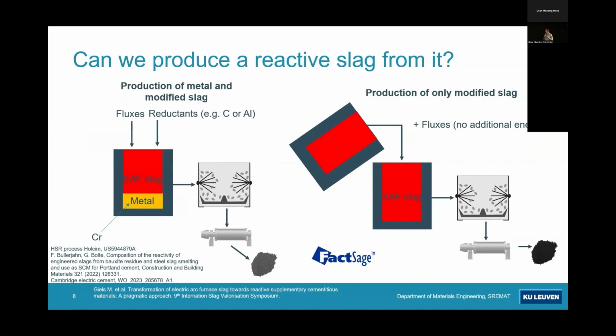There you actually take the electric arc furnace slag, but you add reductants such as carbon. You can also use aluminium, like aluminium drosses can be something interesting to produce a metal. And there you actually extract the metal. You can capture chrome and vanadium. And then you have a slag which looks like blast furnace slag, actually a very easy route. Economically, this is a challenging aspect. The steel producers are not jumping for this because this costs a lot of money.